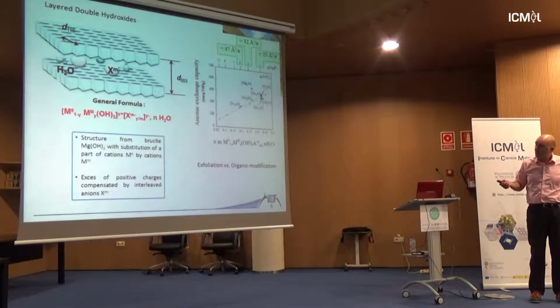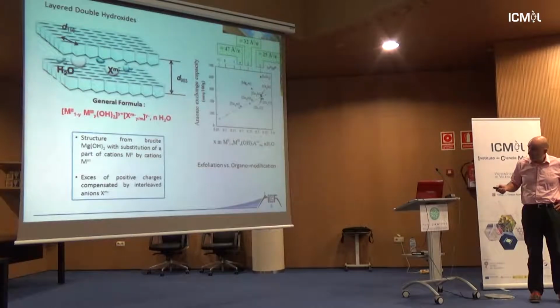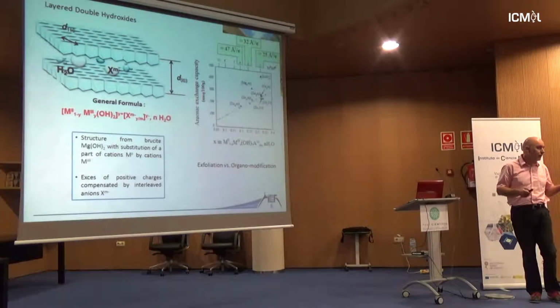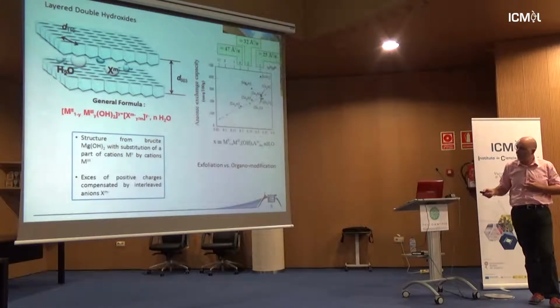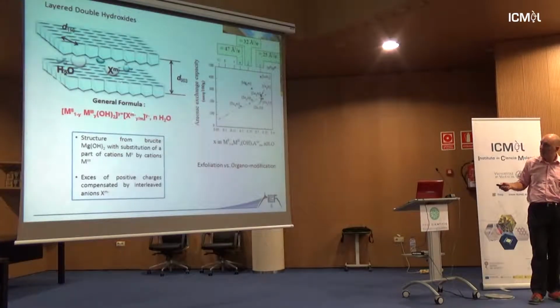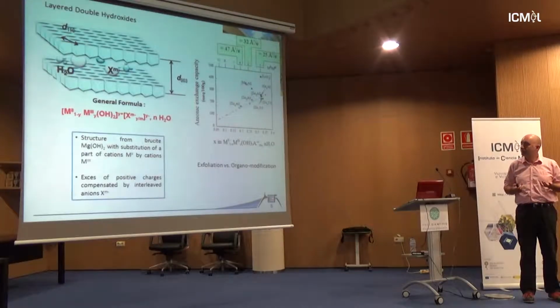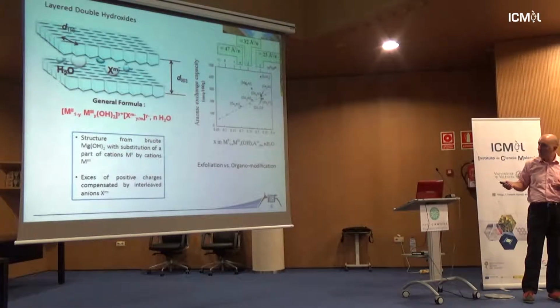So as you know, LDH has a layer structure, planar, edge-sharing octahedra, and it's a substitution of divalent by trivalent cations, starting from brucite, magnesium dihydroxide, to form some kind of complex structure like that. It is positively charged in the layer, and so you have to compensate with the presence of an anion in between the layers. And that gives you all the versatility and the tunability of the LDH structure, because you can change at will the nature of your anion in between the layers. So it can be DNA, for instance, for a gene reservoir, or a superplasticizer for cement, anti-UV, biocide, or anything you want, or something magnetic that you want to put in between the layers.